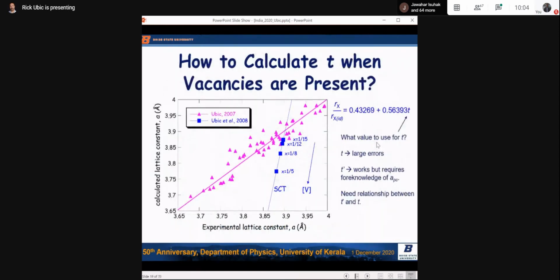So how do you calculate the tolerance factor when there are vacancies present? This is an example we did for cerium-doped strontium titanate. If you assume that vacancies have no size, you get this crazy deviation here from our perfect fit line. Right? So clearly vacancies have a size, but what do you use for T in this equation? If you want to calculate a lattice constant for something with A-site vacancies, you need a tolerance factor. What do you use? If you use tolerance factor without accounting for vacancy size, you get these crazy large errors. If you use t prime, that works great, but of course you need to know the lattice constant first. So it doesn't work so great.